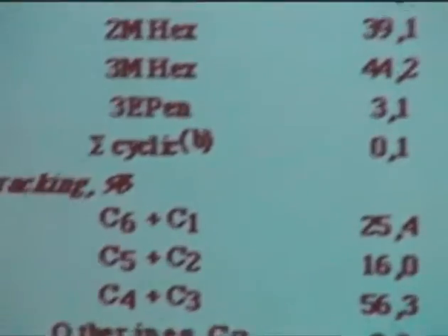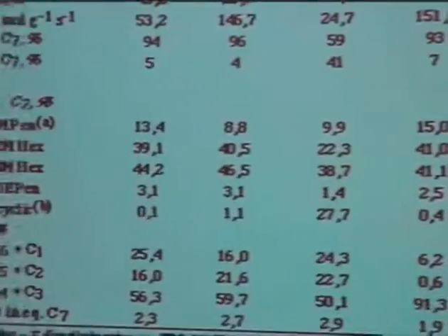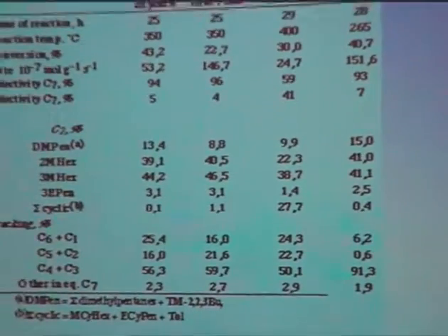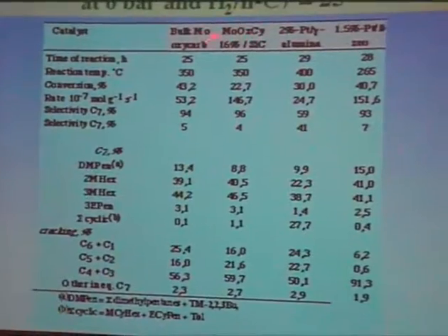If you want to prepare this oxycarbide on a conventional support, like alumina or silica, with a support which contains oxygen, it's almost impossible. Because you have oxygen which is shared by the molybdenum oxide and the support, and it blocks the process of transformation. If you have a support which does not have oxygen and which makes a nice dispersion like silicon carbide, high specific surface area silicon carbide that we are preparing for the program, there you can make it.